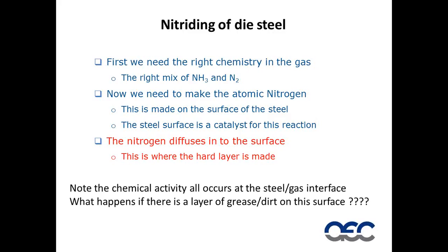Now, as I said, note that the chemical activity all occurs at the gas-steel interface. What happens if there's a layer of grease and dirt on this surface? The reaction doesn't happen. Atomic nitrogen doesn't exist in the gas form in the reactor. Any atomic nitrogen which comes off the surface immediately reacts with another nitrogen atom and forms a nitrogen molecule. So there is no mechanism for atomic nitrogen to go away from where it is formed. Thus, if you have grease, a fingerprint, dirt, dag, or something on the surface, no atomic nitrogen will be formed there, and no nitrogen will go into the surface. So you will not nitride the die where it is dirty.